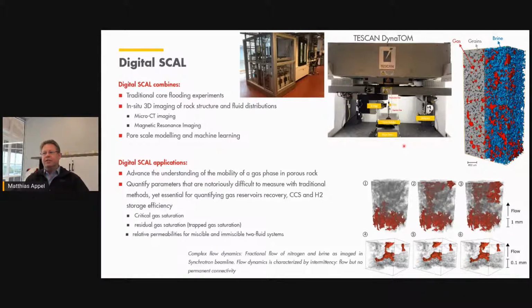You see here an example of a Dynatom device from Tescan, where we have again a small core holder with a small sample and an entire gantry rotating around the sample. You have from the same company the CoreTOM device in your facility, which allows to scan entire large cores, but the core is rotating in front of detector and source. And if you combine that imaging capability with a core flooding capability, you are able to determine the distribution of clusters of pore fluids inside that rock sample. And that gives a huge advantage for understanding the complex dynamic behavior in these porous structures.